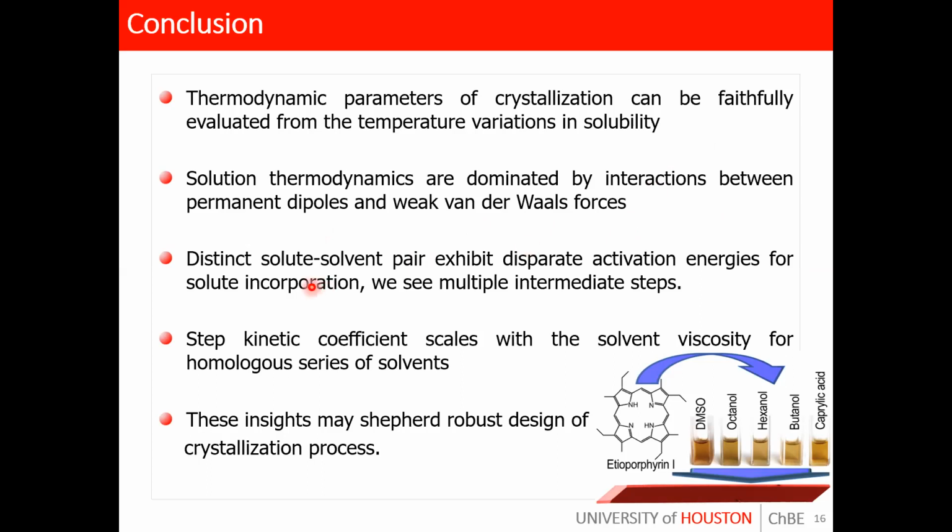But we have also shown that distinct solute-solvent pairs have distinct activation energy barriers for solute incorporation into the kink, and for solvents which are like a homologous series of solvents, that is alcohols, the step kinetic coefficient scales with the solvent viscosity. So these insights will help us design robust